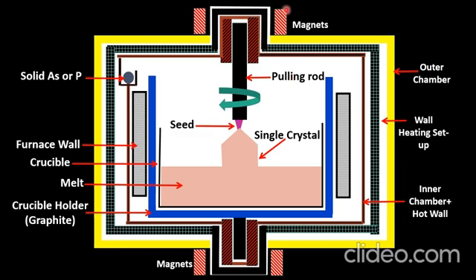So for this, the industrialists use magnets, because semiconductors basically interact with the magnetic field. The magnet causes a magnetic field, which has a specific magnetic field line direction, whereas the semiconductors have an electric field inside them, and the magnetic field and electric field basically combine in the form of Lorentz force. Due to the Lorentz force, the distribution of the dopant becomes uniform, and in this way they are pulled upward with the seed and converted into p and n doped single crystals.